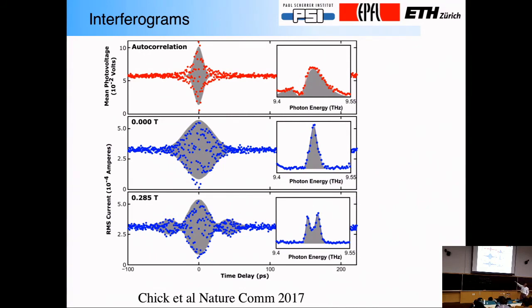If I put a field on, I get these side lobes. Of course, the side lobes come because of the interference between the states in the formerly degenerate orbital. Now these orbitals are no longer degenerate, and I get what amounts to a two-slit interference pattern. But this two-slit interference pattern I observe in time, and I can Fourier transform that into frequency to get the splitting for my two levels. Okay? So all of this physics is just done literally with an ohmmeter now in silicon.